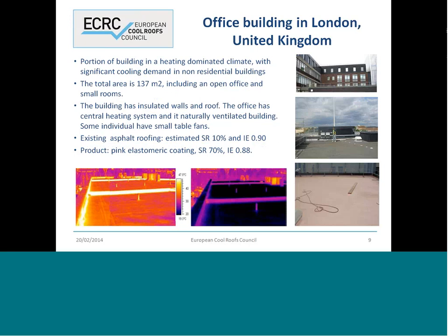The roof has an original asphalt-based covering with an estimated solar reflectance of 10% and emissivity of 0.9, as we can see in this photo on the right. The cool roof application is a cool colored pink elastomeric coating. Radiative properties are 70% solar reflectance and infrared emissivity 0.88. This is a non-white coating, selected to provide some moderate solar gains during the winter and the intermediate season. The two thermal images below show the surface temperature, which is up to 15 degrees lower, before and after the application of cool roof in similar climatic conditions.